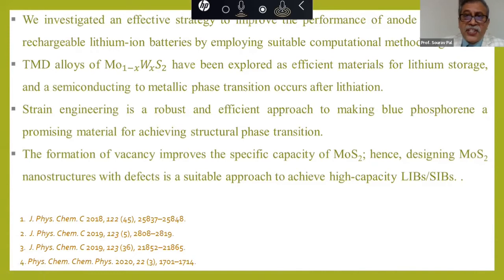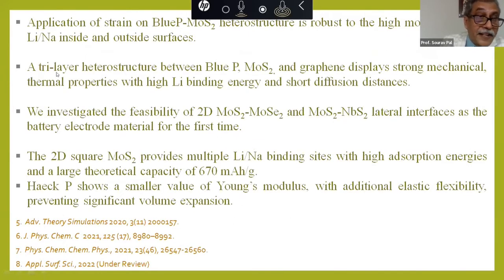We did a lot of strain engineering in the blue phosphorene. Again, it's a promising material for achieving structural phase transition. The vacancy improved the specific capacity of molybdenum sulfide, so we designed nanostructural defects, and that is also a very interesting way. So several works that we have been doing, some of them are listed here. I should say this strain is very important. Very recently, we have looked at a tri-layer heterostructure between blue phosphorene, MoS2, and graphene. And we found that they display strong mechanical thermal properties, high lithium binding energy, and short diffusion distance. This is very important, that the barrier of diffusion also should be very good.